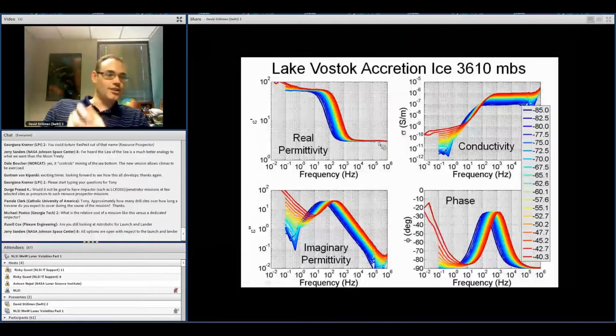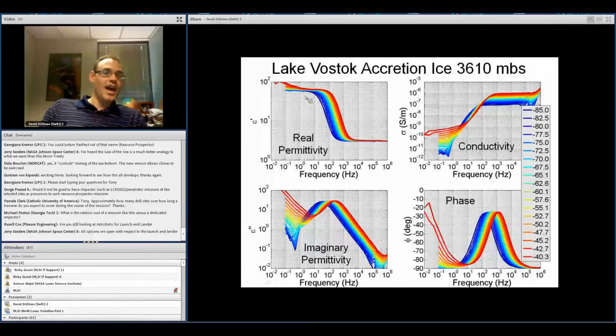At high frequency, these protonic defects, which are the charges that move through the ice lattice and try to store the electric field, can't keep up with very fast electric fields. That's why the permittivity is so low at high frequency. Then at low frequency, they are able to separate fully, and they rest there, and they're able to store a much larger electric field in the sample. Right where this relaxation is going, where we get maximum change, this is where the charges are constantly moving. If we look at the imaginary permittivity, which is a function of the loss, you can see it peaks there. That peak is called the relaxation frequency. So I'm going to plot that relaxation frequency in this next figure as a function of temperature, just to show how temperature-dependent these relaxations are.